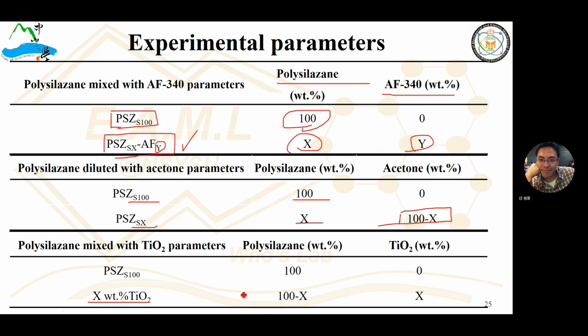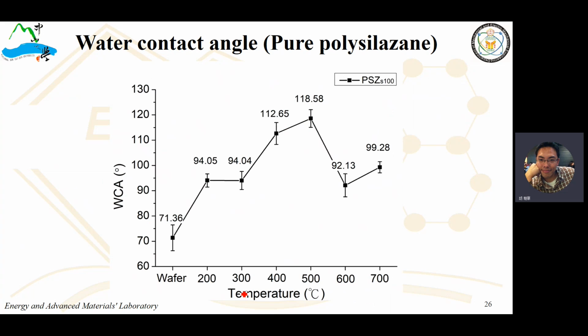Okay. Therefore, we can figure out the contact angle of the pure precursor, pure pre-ceramic precursor. We find out the highest contact angle is at 500 Celsius, right? When the cross-linking or pyrolytic temperature is higher than 500, its contact angle drops substantially.